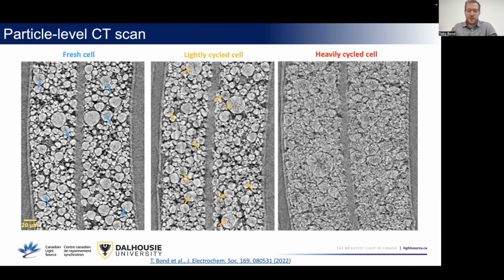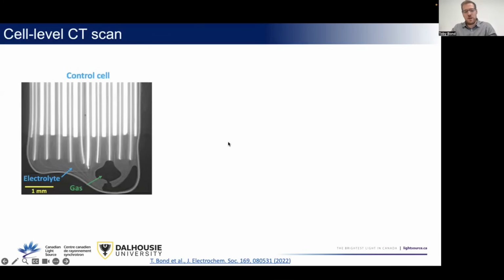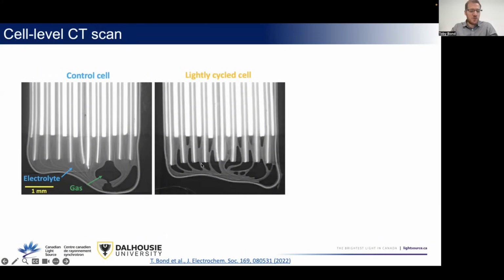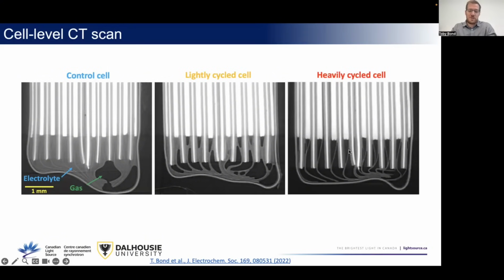The battery is kind of swollen, and that can lead to another effect, which we see if we look at the cell level CT scans. If we start with a bunch of extra liquid electrolyte, which is this light gray here, this dark gray is just pockets of gas. Even in the lightly cycled cell, most of that extra electrolyte is gone after a year and a half of light cycling. And for the heavily cycled cell, it's completely gone. There's nothing left. The reason for that is because we have all that extra space, all of that swelling, and all of what we call pore space up in the electrode. At a certain point, the electrolyte gets sucked up into it.